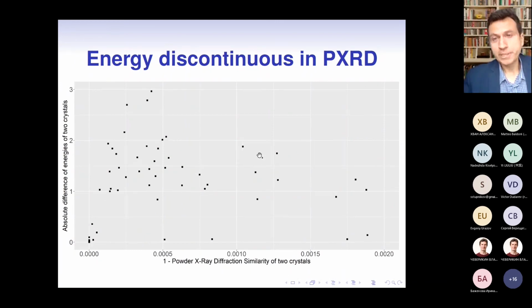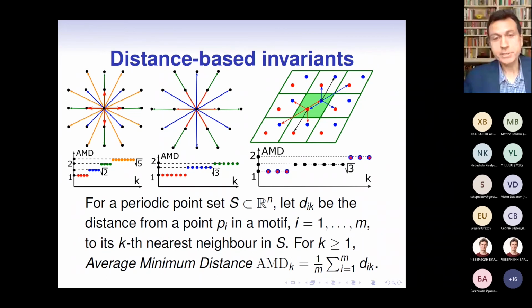So other tools, powder X-ray diffraction pattern. So we have a useful implementation by the Cambridge Structural Database Python API. On the horizontal axis, similarly, you see 1 minus PXRD similarity. So value 0 here means that crystals are very similar. So PXRD is slightly better than RMSD. So there is a smaller number of crystals when PXRD doesn't distinguish them, but energies are different. But nonetheless, it also seems discontinuous. So very small differences, as you see, in PXRD similarity lead to large differences in energy. So that's why we kept looking and designing new invariants, distance-based invariants in this case.